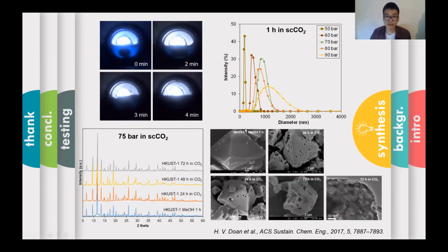The SEM images show that the sample synthesized with a longer CO2 exposure time, after 24 hours, has a lot of macropores without compromising the highly microporous structure. The level of macroporosity can be adjusted by the appropriate choice of CO2 pressure. These results demonstrate that by tuning CO2 pressure and time, we can change the MOF properties such as particle size, morphology, and porosity to obtain designed materials for catalysis, which we have no chance to do in the normal hydrothermal synthesis.